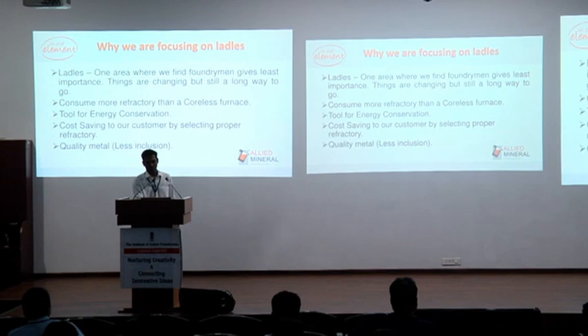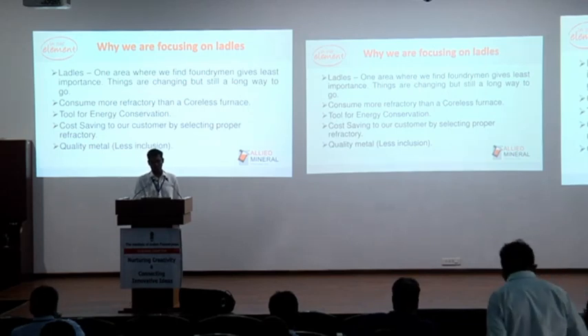Also this helps us in maintaining the quality of the liquid metal. Just think that you are melting a metal of high value in a coreless furnace, but then you take the metal into a ladle which has been lined with sand, and the sand will erode fast and get into your metal and create rejections and inclusions. It's again a huge cost, so we always recommend a proper selection of refractories to get rid of such losses.